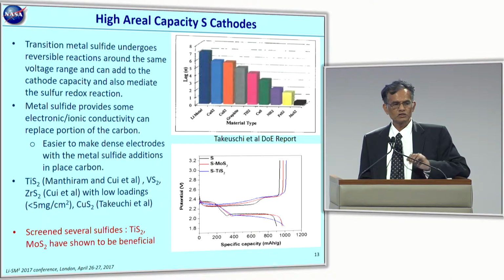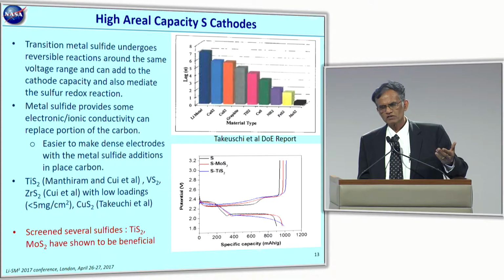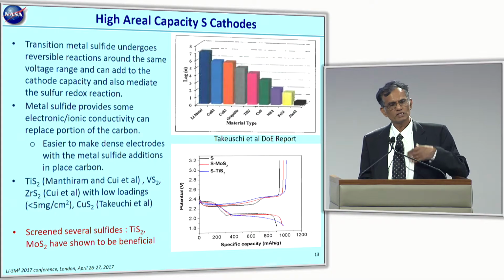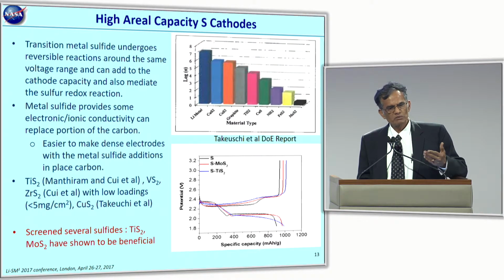And that's where we took a detour, and started looking at how to modify the sulfur cathode. We know that historically there were known metal sulfides like titanium disulfide and molybdenum disulfide, which are very reversible cathodes. Interestingly, they also have voltages in the same range as the sulfur cathode. As you see on the top right here, the conductivity of these metal sulfides is comparable, if not better, than graphite. So our approach was to replace some of the low-density carbon, which is used as a conductive diluent, with a metal sulfide. In particular, we used TiS2 and moly.